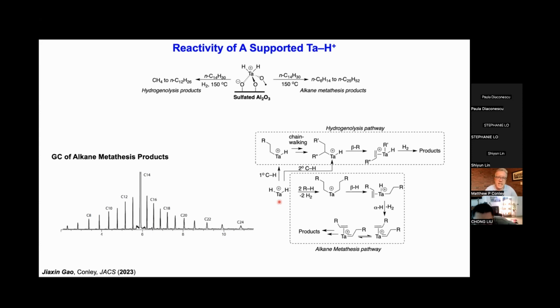For the alkane metathesis reactions, we must be activating the primary CH3 group, because if you activate the secondary group, that would install a branch in your final product. So we think we're getting these dialkyls that undergo beta H elimination, followed by alpha H elimination to give us the olefin alkylidene intermediates that undergo olefin metathesis and subsequent hydrogenation to give us our linear product shown here.